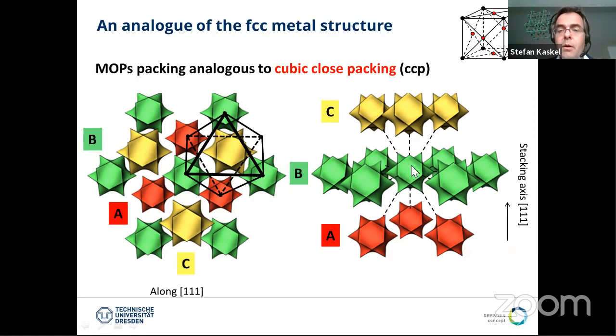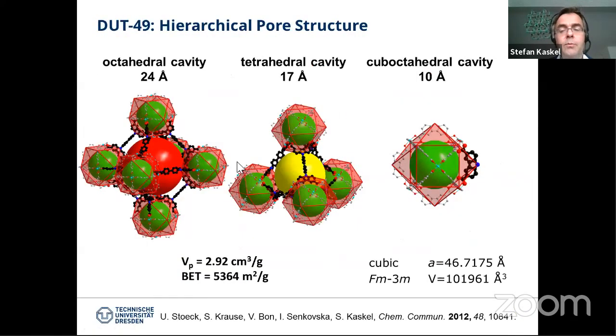So each MOP is surrounded by 6 MOPs in one layer and 3 above and 3 below. And in between, we have the tetrahedral and octahedral voids. But as compared to a normal copper metal structure, here the spacing is much larger and the voids are much larger. So this is a single crystal structure, and the voids are 2.4 nanometer, 24 angstrom. This is the largest pore, the octahedral void, and this gives us this huge pore volume and high specific surface area, ultra high surface area, as I've pointed out in the beginning.